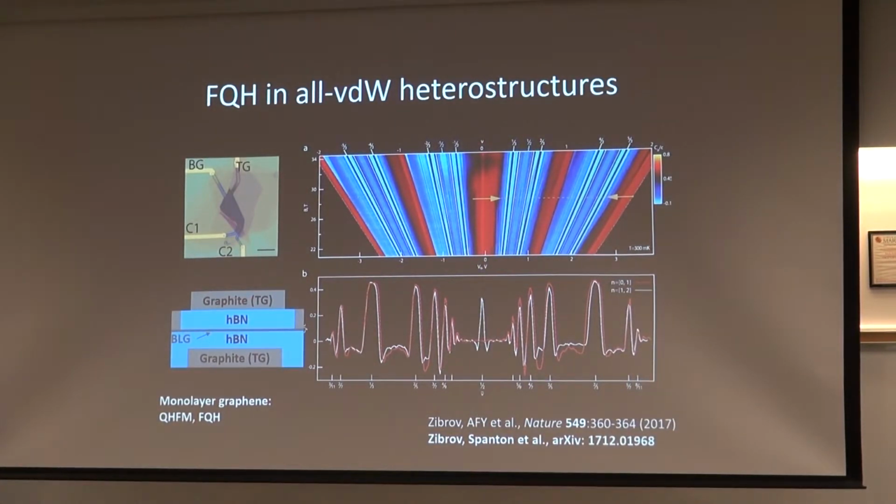And so this patch effect, of course, once you know what it is, it's very easy to find lots of literature about the patch effect. But that was what was limiting. That essentially made a long wavelength kind of disorder potential for the graphene. Luckily, the way we assemble these, it's relatively easy to replace some patch effect riddled metal film with a single crystal and a single crystal facet in the form of graphite. So what we did was start to build devices where essentially everything, the gates, the dielectrics, the channel itself, and the contacts are all made of single crystal van der Waals materials.